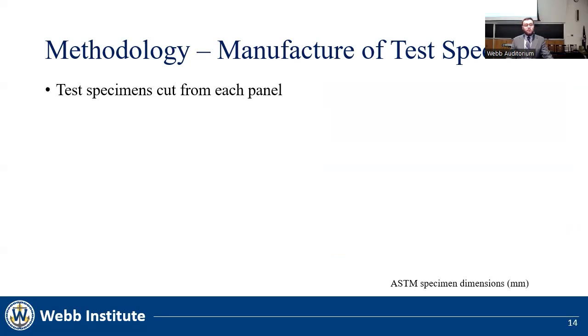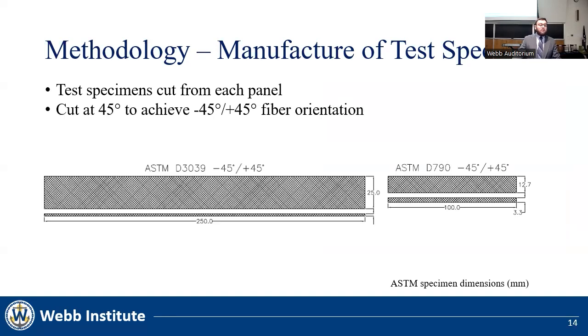Once these panels were cured, test specimens were cut from each panel. Some were cut at 45 degrees to achieve a negative 45, positive 45 degree fiber orientation, as can be seen here in the tensile and bending test specimens.